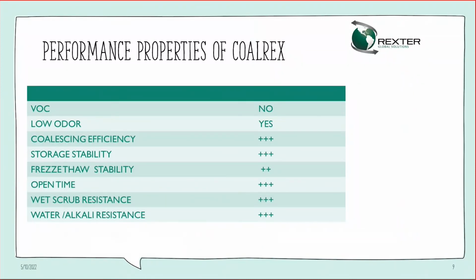Then we have here the performance properties of our COALREX. We understand by the three plus signs that it is excellent, and by the two that it is very good performance. So we have that it has no VOC, very low odor, and coalescing efficiency is excellent. Storage stability is excellent, also because of the excellent hydrolytic stability of the product. The freeze thaw stability is also very good. The open time is excellent. The wet scrub resistance is excellent, which is important.